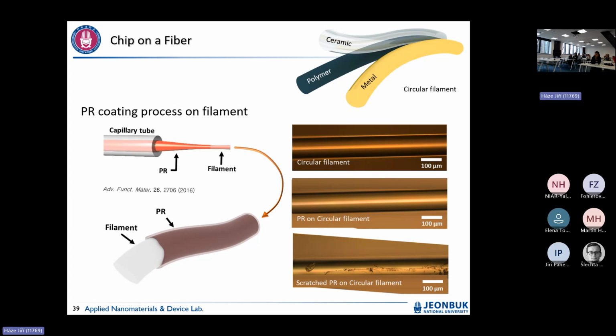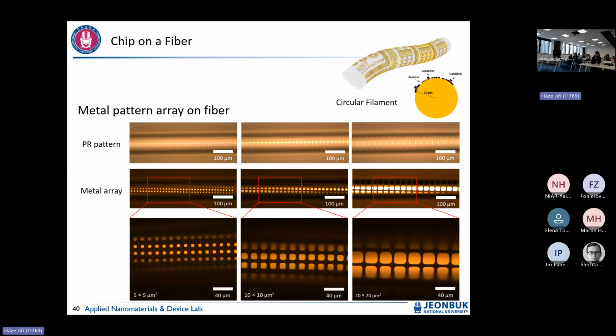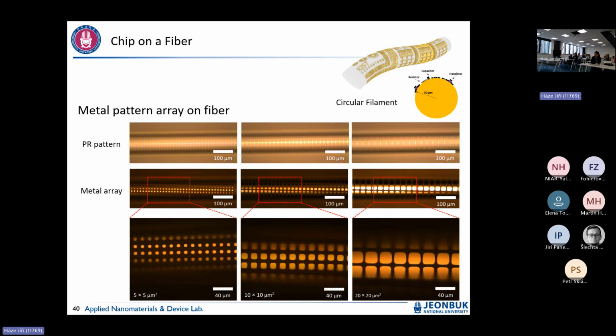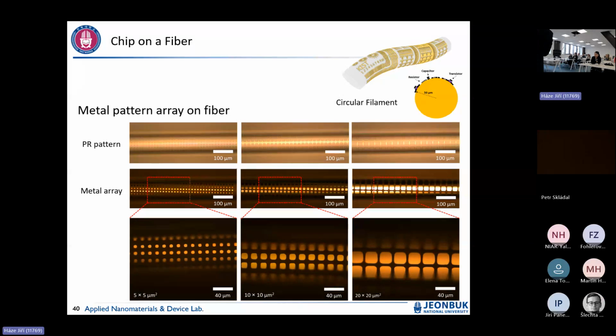So we tested whether it really works by applying the lithography process. You can see here, right at the development, we found a really nice pattern: 5 micrometer, 10 micrometer, or 20 by 20 micrometer. Right after deposition of metal, for example aluminum, we do a lift-off process. You can see here, we can get a really nice pattern on the fiber. But unfortunately, it's really hard to get the focus right. If we focus on the center, the rest is off.